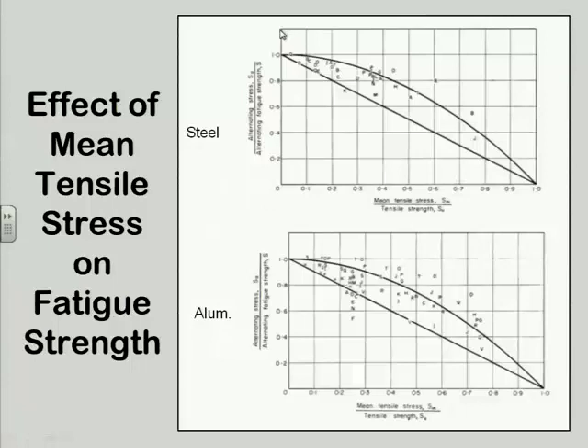So if I have no mean stress whatsoever, then I'm operating on this axis, and this value shown here as 1, because everything's been normalized, is the endurance strength or the fatigue strength of the material, which is that number that we would get by first taking the ultimate tensile and cutting it in half, and then adding the load factor and the surface factor and all that stuff till we get down to something around 30%. So that's what that value is on that axis.